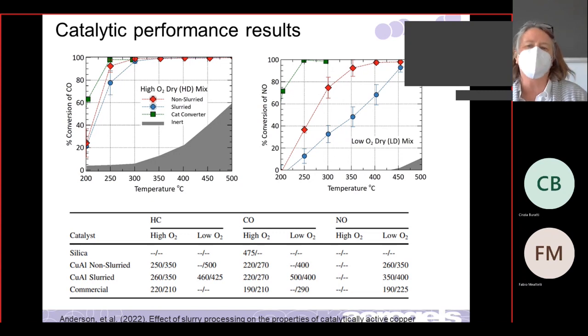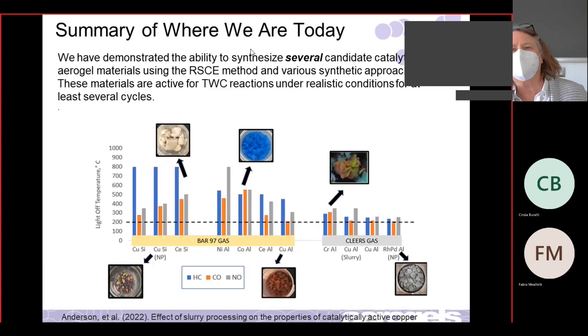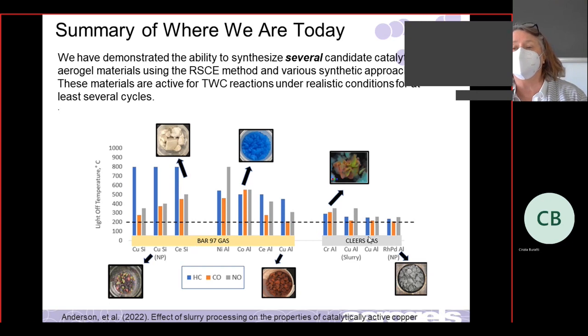using copper too. So this is a summary of where we are. This is light off temperature versus all of the different types of aerogels we've made. I should say the initial gas we used had a hydrocarbon that was hard to convert, and the cleaner hydrocarbon is better. So we see a difference when we went to the recommended thing. Again, low is better. The blue is the hydrocarbons, the orange is the CO, and the gray is the nitrogen. Here's some of the early stuff with the copper silica. It didn't do particularly well. This is ceria silica, also not that great.